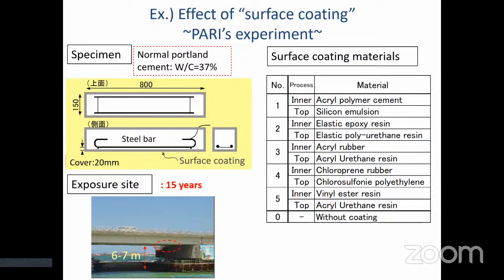This slide shows one example of the effect of surface coating from our experiment. Concrete specimens with 5 types of surface coating were exposed for 15 years in a marine atmosphere environment. Here, this coating was applied before exposure.